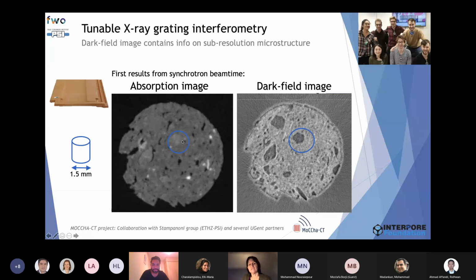Now what you see, for instance, if you look at the blue circle, here there is a zone where you see it is like a grain. But difference in gray values can be due to a difference in composition, but it can also be that you have, for instance, a microporosity present.